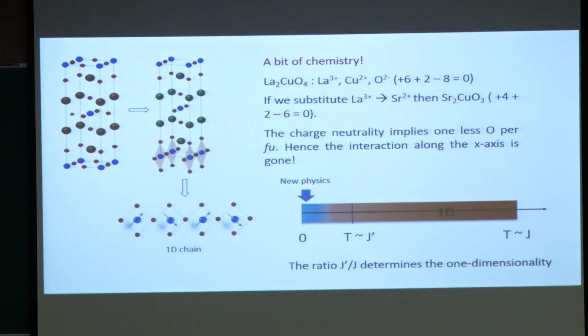Okay. So, now the coppers can interact with their nearest neighbor only along this crystallographic direction. Why? Because along this direction the super exchange path is removed. Do you see that? The super exchange path has been removed in this case, because there is no oxygen in between. All right. The other change that you should notice is that now copper is in a square planar coordination, right, because the apical oxygen is completely gone. Okay. So, these are the two changes that have taken place when I replaced lanthanum by strontium.